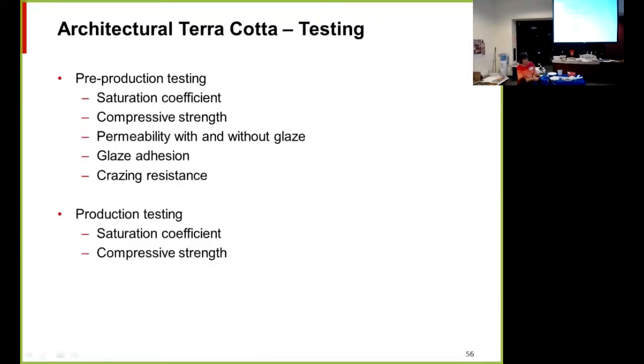These are the different requirements that we have for pre-production testing. The first two, saturation coefficient and compressive strength, have to do with the quality of the bisque. And then you also want to make sure that the glaze is not permeable and it's well adhered and it's not going to craze. Then in production testing, usually we don't require all those tests, only saturation coefficient and compressive strength. And then during production, you're getting these every so often. You can compare them to the pre-production. And if you start to see some big change, then you know maybe you need to go back and test the other things to see what's going on.